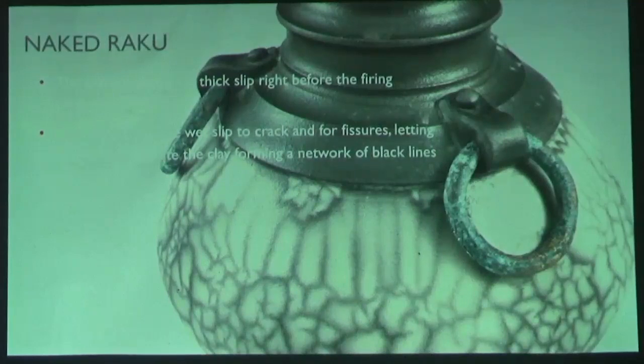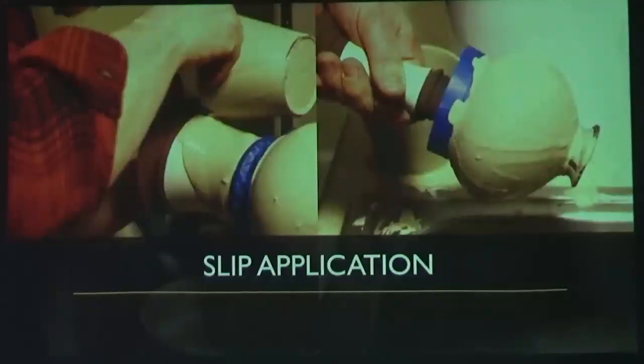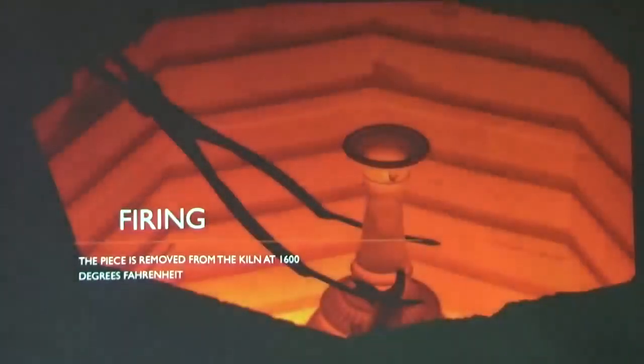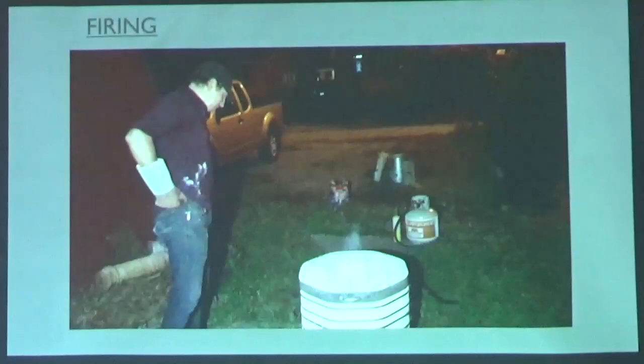Wow. Now I'm firing at a much lower temperature, at about 1900 degrees for the first firing, and then the actual raku process I'm doing is at about 1600 degrees. I'm not sure how high my kiln can handle. I haven't tested that, and I don't really care to. I kind of like my kiln. Anyway, so that's burnishing and preparing the clay surfaces for these kinds of decoration.